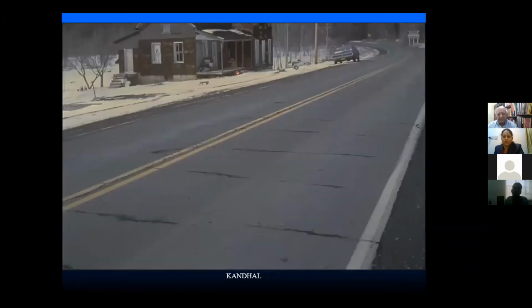Here I'm showing a picture of non-load associated cracking in the state of Pennsylvania, in the north of the USA, where I served as chief asphalt road engineer for 17 years. You can see all these are transverse cracks. They happen overnight, when the pavement was chilled at a very rapid rate. At first the width of the crack will be very small, but with time they become prominent and wider, as you can see here. They appear like something that happens on a concrete road, but here is a bituminous road. So we have to use a proper, softer binder, which will be softer when the temperature is lower.